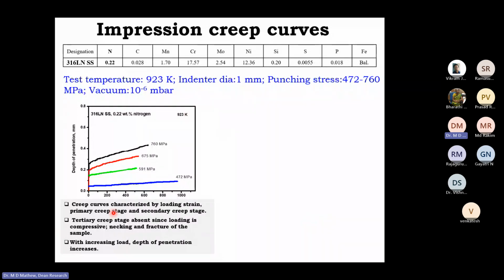So this graph gives you the results of impression creep tests on 316 LN stainless steel at 923 Kelvin at four different loads, for stresses from 472 to 760 megapascal. You see here you get typical creep curves at all the stresses, and as expected, as you increase the stress, the creep curve moves up when you plot depth of penetration versus time. The creep curves are characterized by a loading strain, a primary creep stage, and a secondary creep stage. As I mentioned, there will be no tertiary creep stage in impression creep because there is no necking and no fracture. And with increasing load, depth of penetration increases.